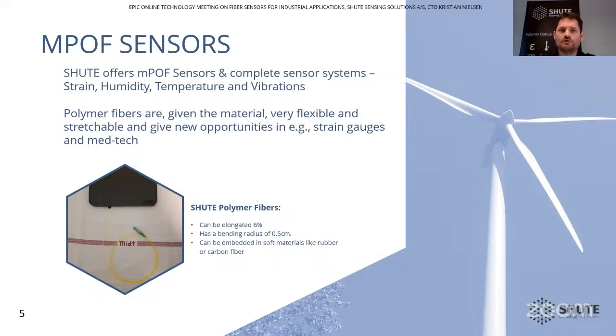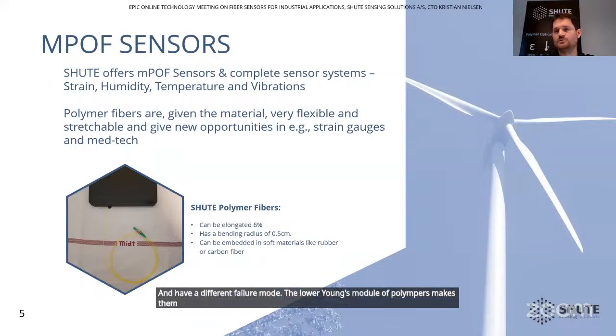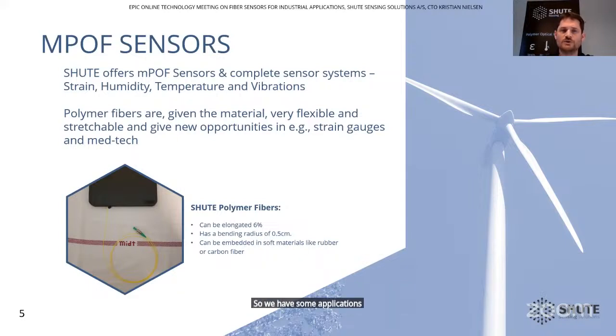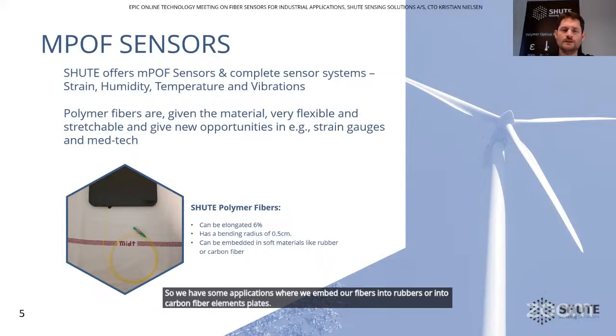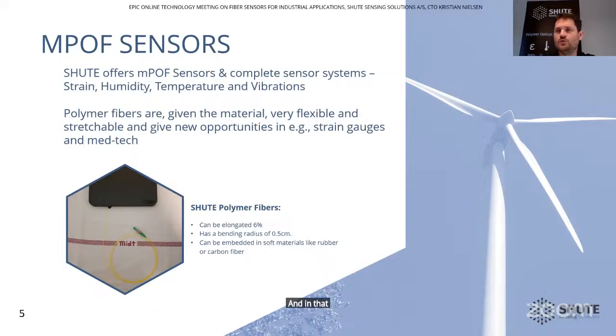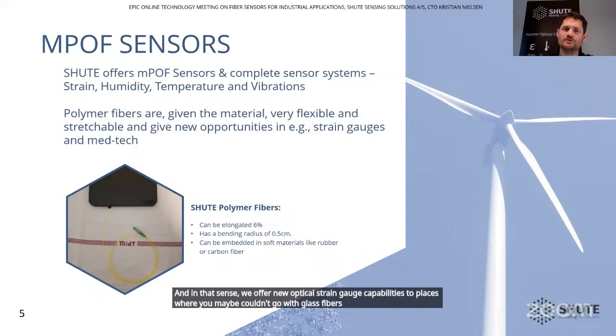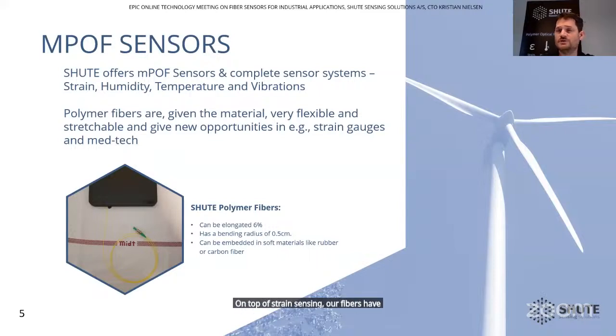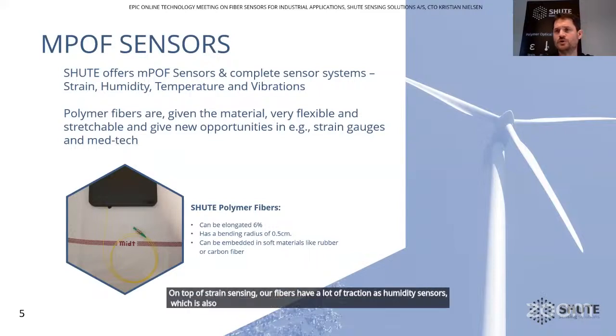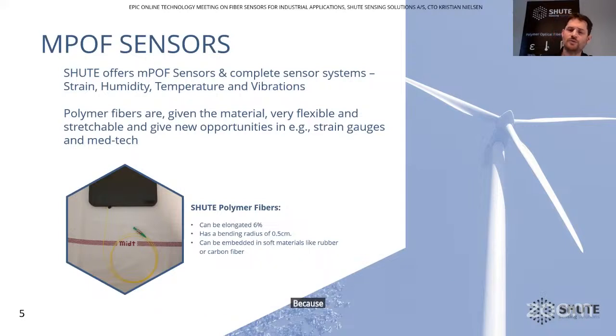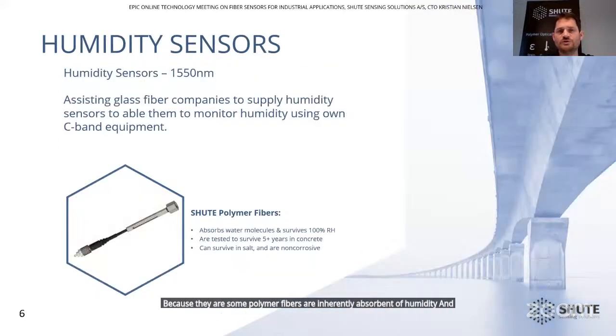The low Young's modulus of polymer fibers makes them ideal for picking up very small stress levels, and also makes them compatible with soft materials. So we have some applications where we embed our fibers into rubbers or into carbon fiber elements, plates. And in that sense, we offer new optical strain gauge capabilities to places where you maybe couldn't go with glass fibers because of their inherent stiffness. On top of strain sensing, our fibers have a lot of traction as humidity sensors, which is also a fairly unique capability of polymer fibers, because some polymer fibers are inherently absorbent of humidity, and that makes them very good as humidity sensors.